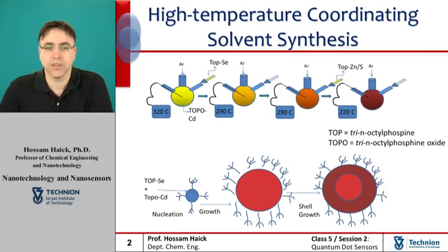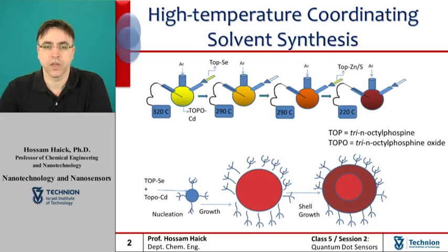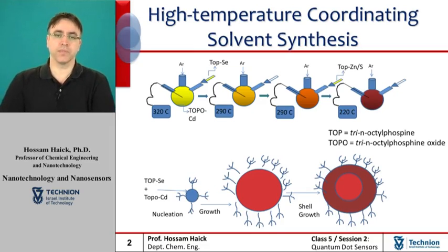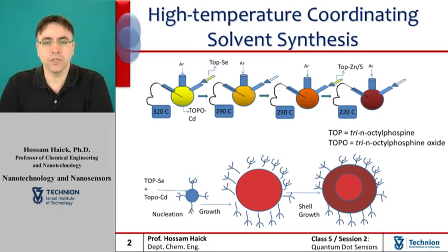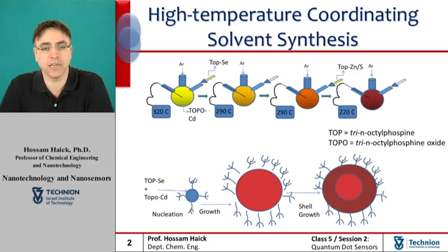Under these conditions, particle nucleation takes place rapidly, followed by epitaxial growth and nanocrystal annealing at slightly lower temperature. During the growth period, the quantum dot size can be monitored using a spectroscopic probe within the reaction flask or by examining fractions taken at various intervals.